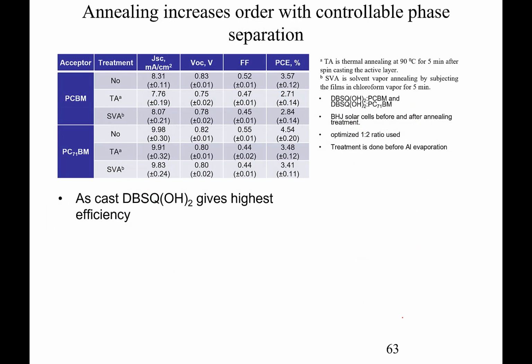What we found again was that we get highest efficiency actually with PC71BM, but we always find that, as we've seen before, the as-cast film seems to give us the high efficiency. In recent data, we've managed to do better with the annealed films in here, but it's quite subtle. But the point here is,